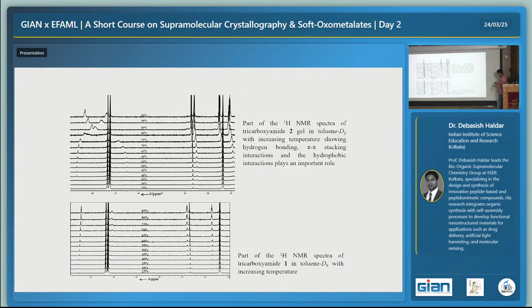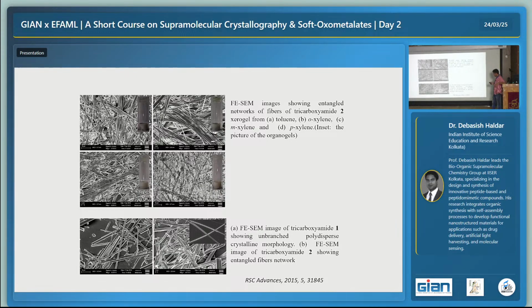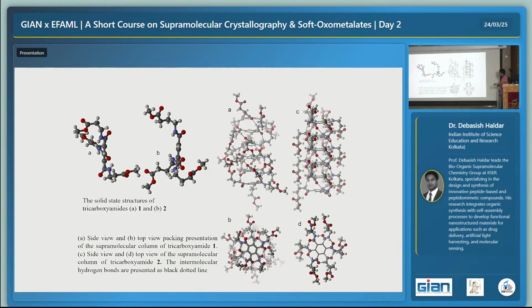So again we have started with NMR, with temperature dependent NMR, and what we have seen is that when it is beta amino acid there is a different kind of packing, and when it is gamma amino acid there is a different kind of packing, and that's why it is showing different behavior. So this is what we are saying. When it is beta amino acid, it is forming a fiber-like structure, and that fiber further self-assembles by entanglement. But when it is gamma amino acid, it's straight fibers, and those are not entangled, and that's why we are getting two different structures.